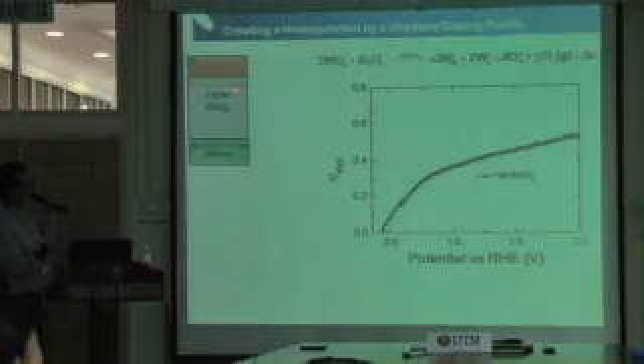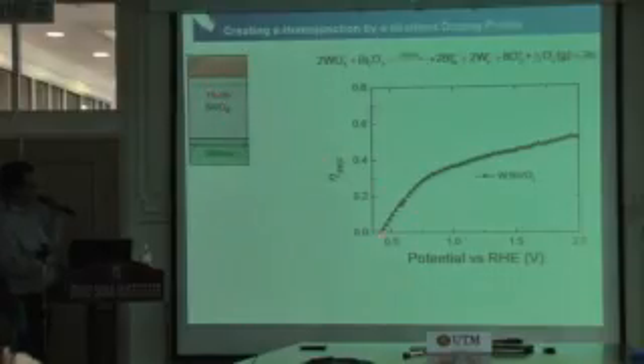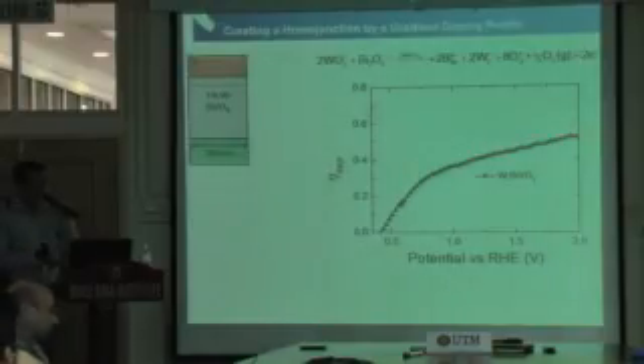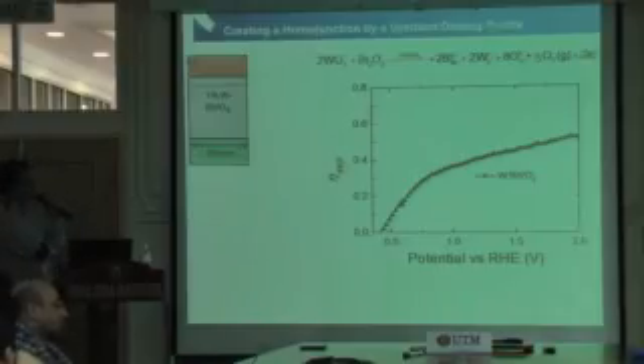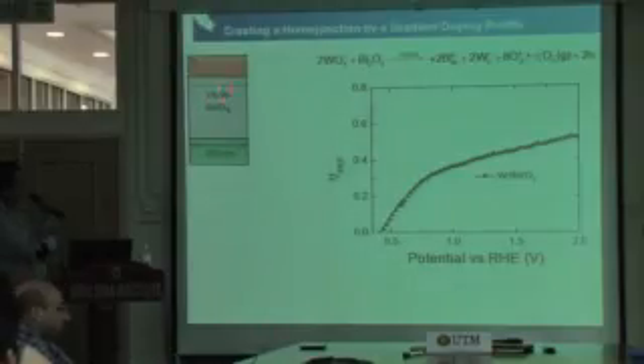And we did that. This is a homogeneous doping of 1% tungsten in our bismuth vanadate, and the carrier separation efficiency is now improved slightly. It's now about 50%, so it's improved rather slightly. We cannot improve this further by just doing homogeneous doping. We tried increasing the concentration here, but it actually goes down again. So we thought of some other tricks.